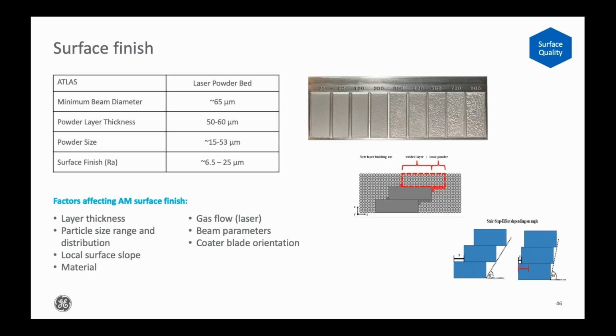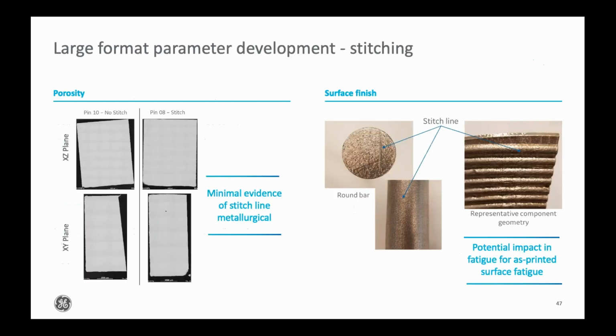Right now, as it says there, the surface finishes that we were seeing on these Atlas prints were somewhere between 6.5 to 25 micrometer, based on the orientation of where the surface was measured, whether it was on a vertical wall or on some sort of angled wall, like a downskin, which is shown on the bottom right. Next slide.